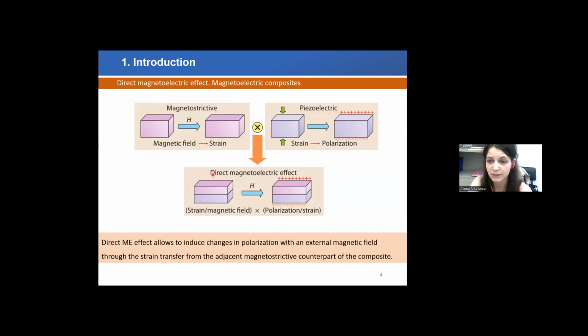In these composites, there are usually two phases. One phase is the magnetostrictive phase. This is the phase that can generate strain under the action of a magnetic field, and in our case, this could be our iron gallium films. And then the second phase is a piezoelectric material. Piezoelectrics have a property to generate charges, to change polarization state when they are strained.